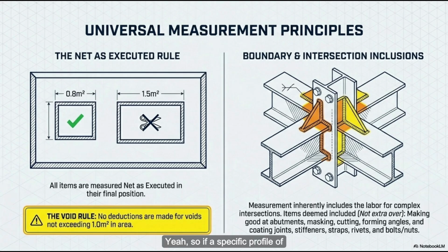Wow. Yeah, so if a specific profile of corrugated steel has a surface area that's, say, 1.4 times larger than its flat footprint, the contractor just has to know that. Yeah, they have to calculate that corrugation factor themselves, and then they bake the extra labor and material costs into their initial unit rate. Because the client is literally just buying the coverage area on their blueprint. Exactly right. The burden of calculating the physical reality of the metal falls 100% on the contractor.